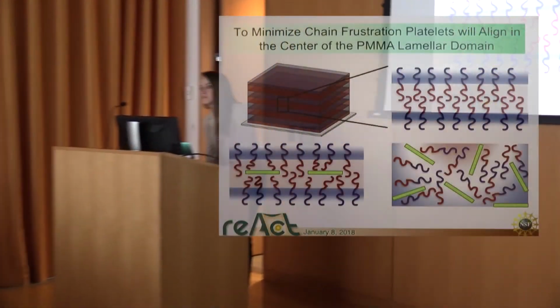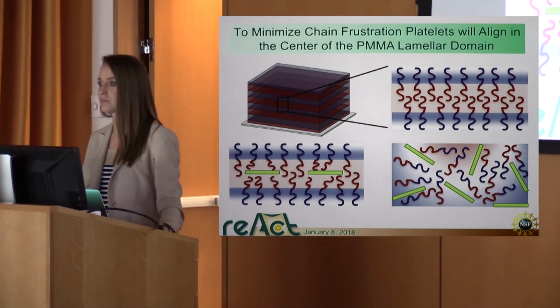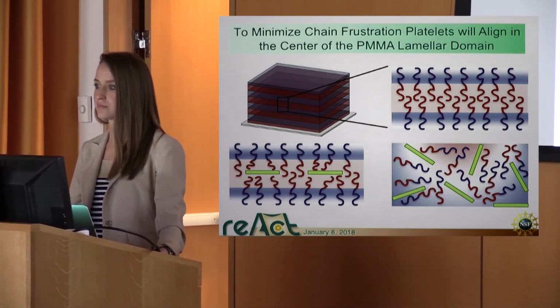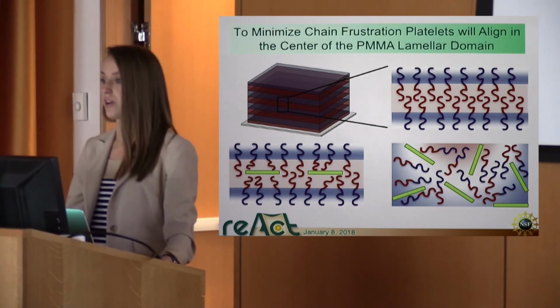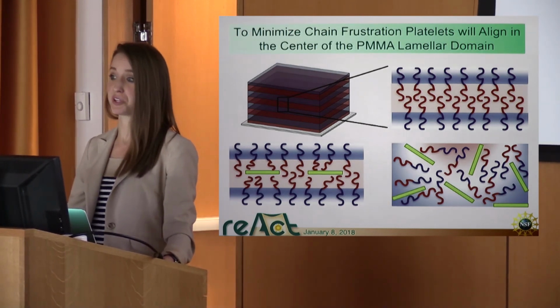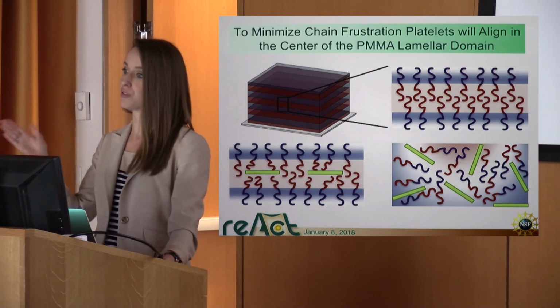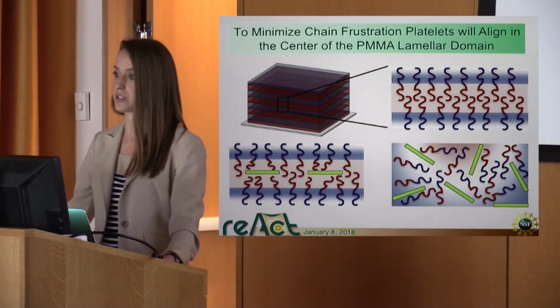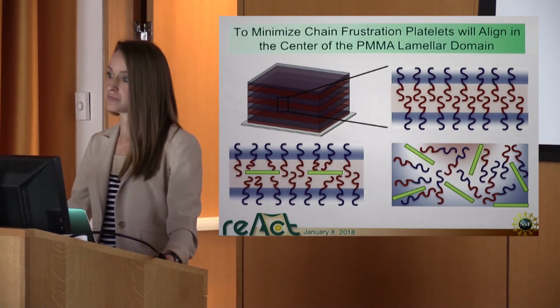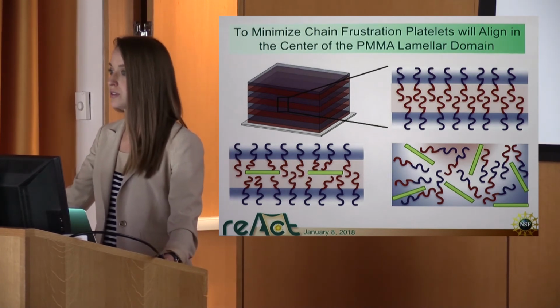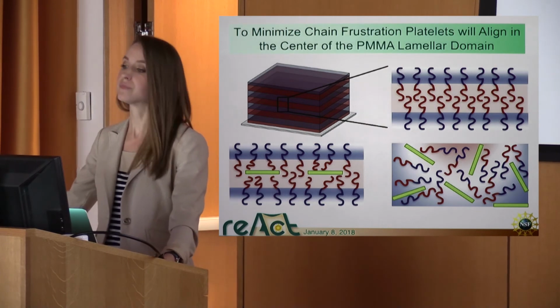To go back to your interpretation regarding the frustration, I'm going to ask a geeky question. Adding all those platelets, because you go really far, could it be just that you're moving in the phase diagram because you're increasing the volume fraction of one of the two blocks artificially? Yeah, certainly. And that's actually something we were talking about probing this morning, going off of the lamellar region and incorporating the particles to see if we can shift back into the lamellar region. Or maybe adopt a cylindrical morphology. Right, yep. That's smart.